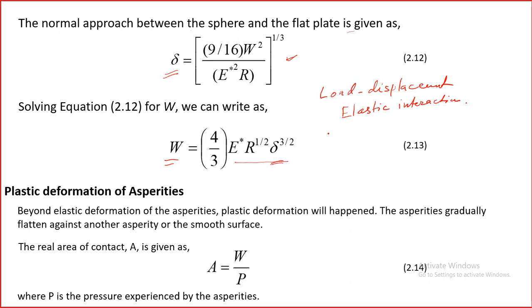This is valid for most polymers and elastomers. But for metals, it may not be very valid because metals will undergo plastic deformation quite soon. So, plastic deformation of asperities: beyond elastic deformation of the asperities, plastic deformation will happen. For example, initially we have this asperity and this flat plate, and let's say it is under some deformation here. But as we increase the load, as W increases, this will go further down, and we will see that it starts flattening if this is the softer material. The softer material will deform, and this deformation is plastic deformation. So you get a flat surface after plastic deformation.